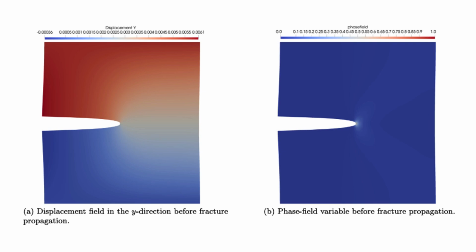Because you have exact analytical solutions for that. You can calculate the peak stress, the failure point, on paper. So they ran the simulation and checked, do the numbers match the math? And did they? They did. Good agreement. It validated the basic setup, the AT2 model they chose, and it also showed something interesting about that model. Oh, what was that?